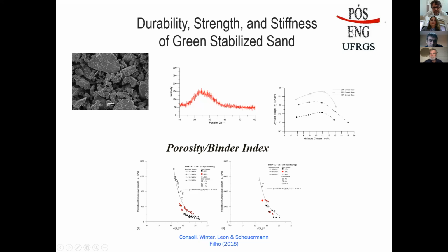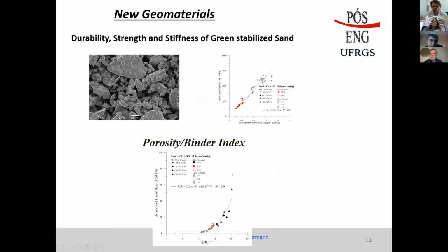with unconfined compressive strength, also with, let me show you, also with initial shear modulus, and unconfined compressive strength, you can have a unique curve here. And finally, this index also controls what we could call the durability of this material. So regardless of the way that you are going to mix with different dry unit weights, different glass contents, lime contents, or any other kind of binder that you might use, you have a unique curve here.